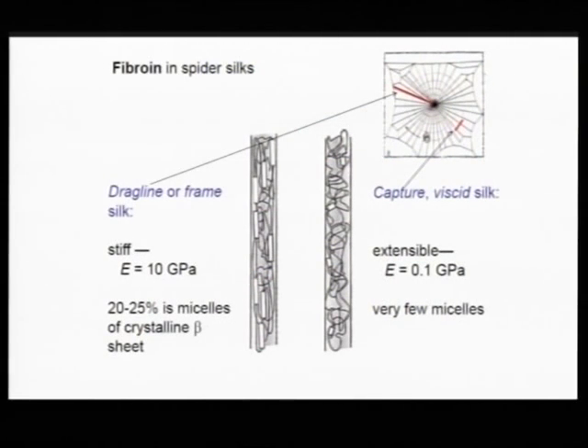So we know what we want from the point of view of the spider. Does the spider actually pay attention to this? Well, yes, it does. When the spider makes a web, it has two types of thread in the web. The ones that are radial are those straight lines you see top right. They need to be stiff because you want to hold the web in place. And then the other ones, which form a sort of spiral from the center, are the so-called capture threads. Those are the ones that are going to be used to catch the fly. You don't want those to be stiff. You want those to absorb lots of energy, so you want a low modulus. And with exactly the same chemistry of all of these threads, the same chemical composition, the spider manages to make threads for the frame that has a modulus of 10 gigapascals, and for the capture lines, a modulus of 0.1 gigapascals. In other words, a factor of 100 different in the modulus is engineered by the spider for this purpose.